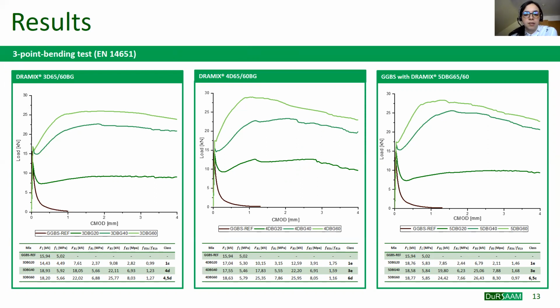In the table under each diagram, it is possible to see the classification of each mix following the recommendation of the fib Model Code 2010. Every mix is classified with a number which represents the characteristic residual flexural strength corresponding to a CMOD of 0.5 millimeter, and a letter which represents the ratio between the characteristic residual flexural strength at a CMOD of 2.5 millimeter and at 0.5 millimeter.